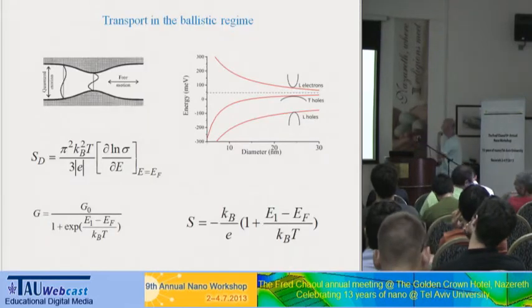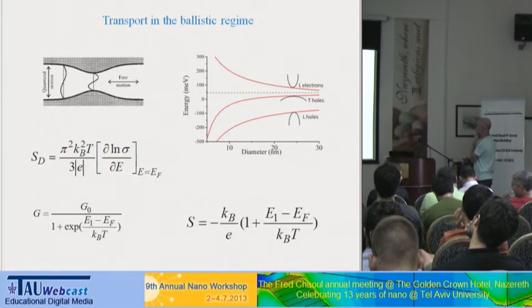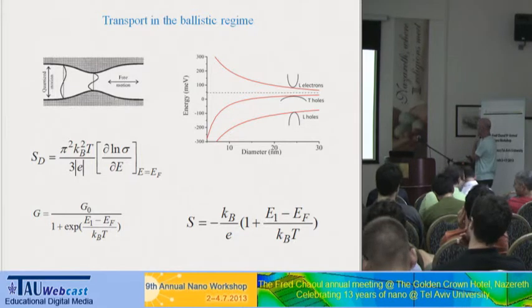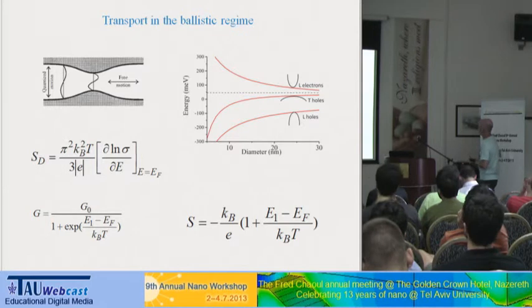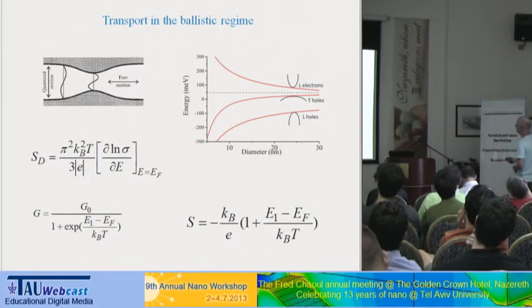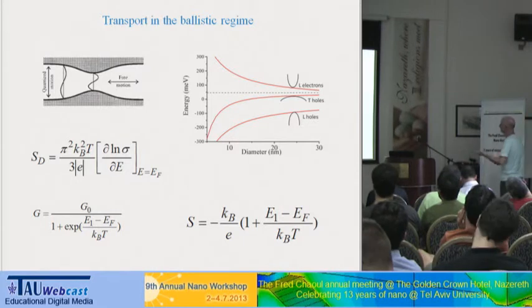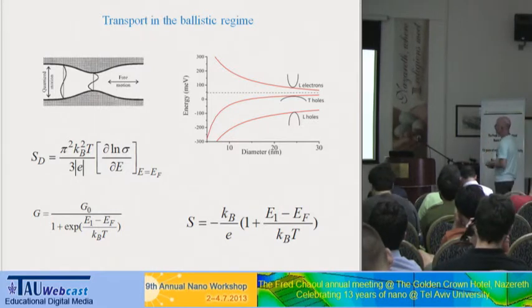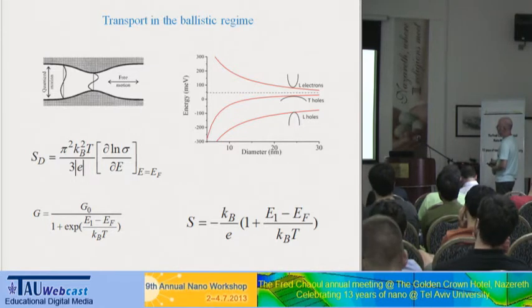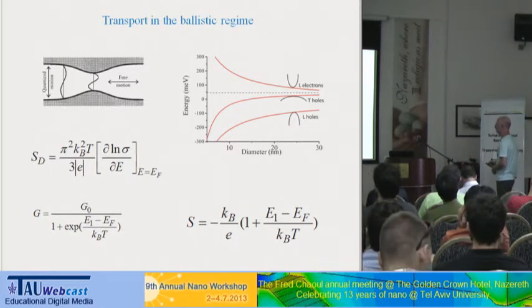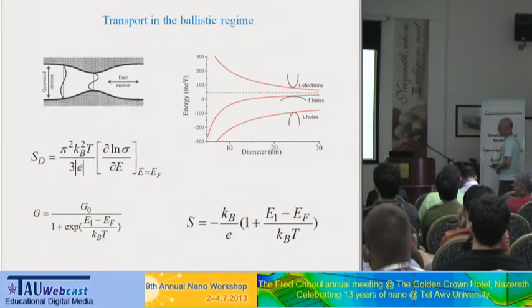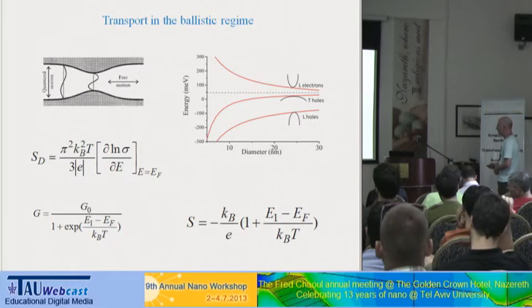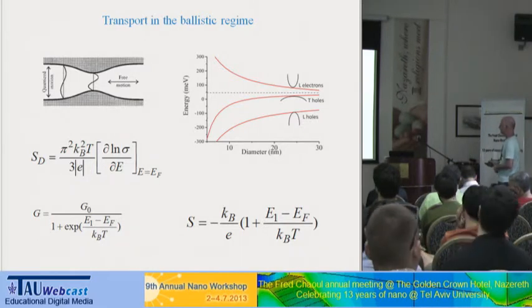So theory suggests the following. Suppose that we have a wire and we shrink it, so that we have the quantized behavior that we have here in the middle. So here are the band edges of bismuth, and as you make this size smaller and smaller, you get a larger gap between the bands. And if you just model it as a one-band model, you can see that the Seebeck, which is proportional to the derivative of the ln of the conductivity. And here everything is ballistic, so the conductivity is G naught divided by this argument here. I won't go into the mathematics.